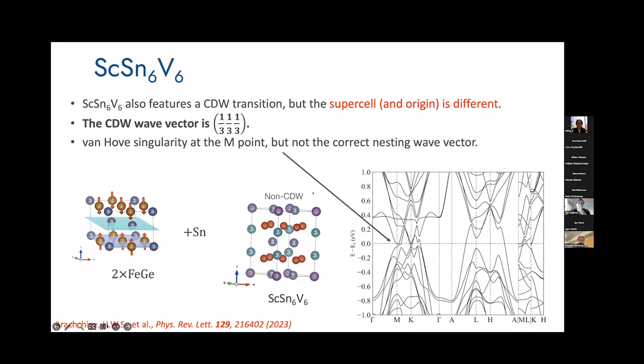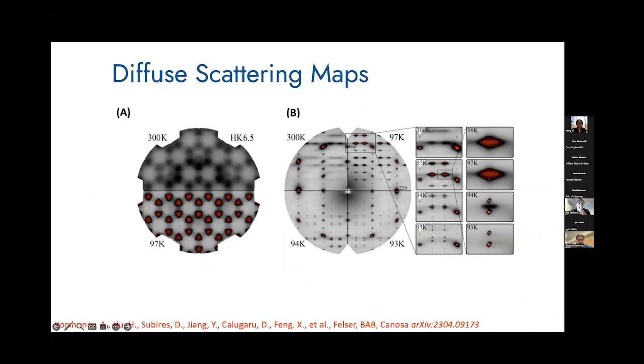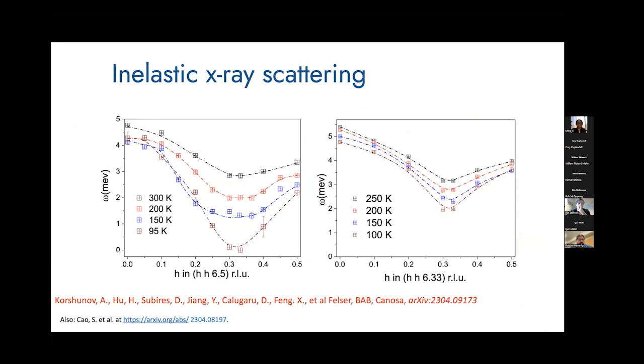And the experiments of my collaborator, Santiago Canosa, showed the diffuse scattering maps, which showed a collapsing phonon, of a second order phase transition type, at 1/3, 1/3, 1/2, also called the H point. And you can see the collapse of the phonon around the CDW phase transition at 1/3, 1/3, 1/2. And you can see the fact that the 1/3, 1/3 phonon does not collapse here. And the CDW is at this wave vector.